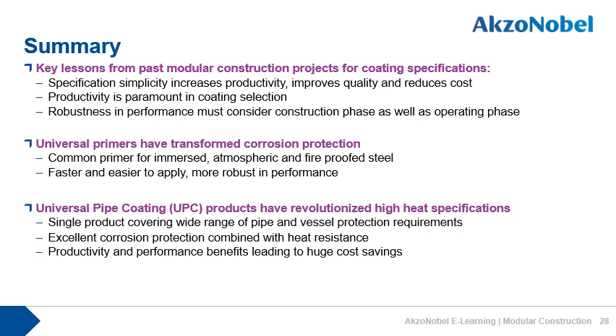Universal primers have transformed corrosion protection, and AkzoNobel have pioneered the use of universal primers with the Intershield 300, and they act as a common primer for immersed, atmospheric, and fireproof steel. They're faster and easier to apply and more robust in performance compared to traditional coating systems such as the zinc epoxy polyurethane 3-coat system.